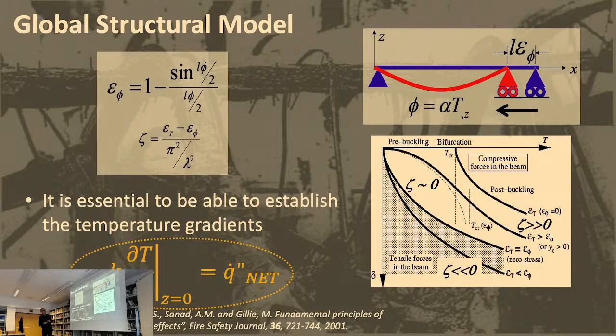And now, what do we have here? If we look at the thermomechanical behavior of just a simple beam, if we heat the beam, there's going to be bulk heating that is going to result in thermal expansion, but there's also going to be temperature gradients because of the imposed heat flux, and those temperature gradients are going to expand the lower fiber more than the upper fiber, so you're going to get curvature. As a result, the difference between the bulk heating and the reduction due to curvature is what is going to give you effectively the stresses and strains within the mechanical system. Okay? Now, you can normalize that. Here's the bulk expansion minus the shrinkage, and you can do a simple geometric analysis to find out what the shrinkage is, and then you can demonstrate by modeling when it's going to buckle, what kind of deformations you're going to get.